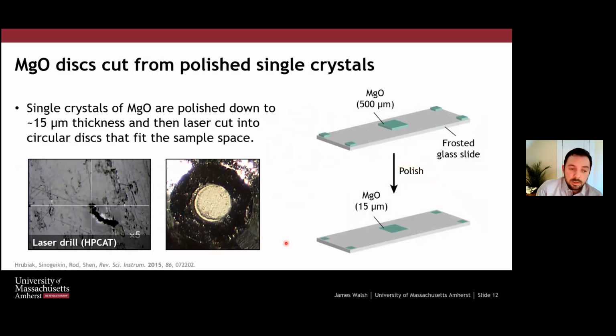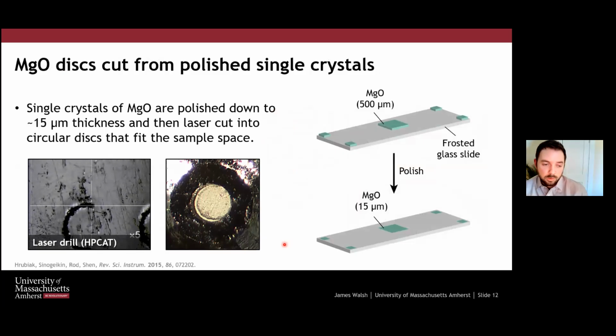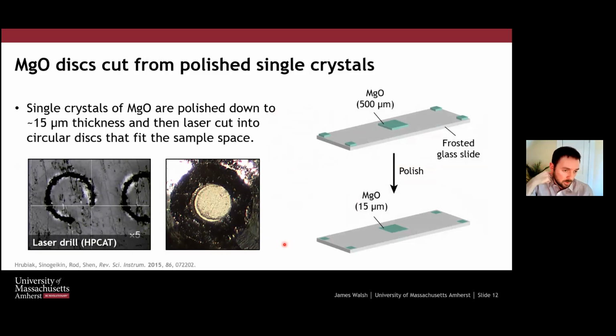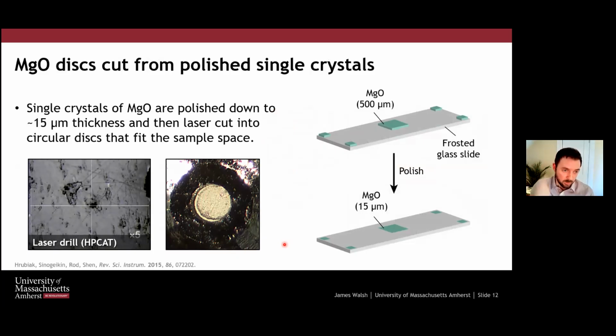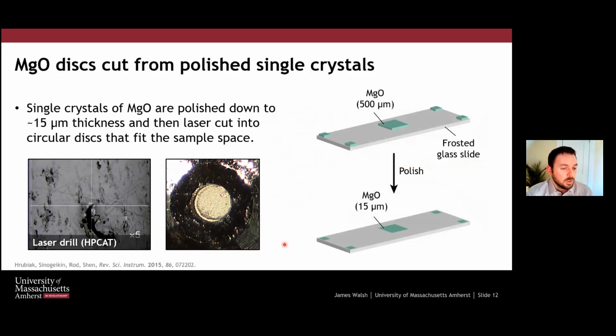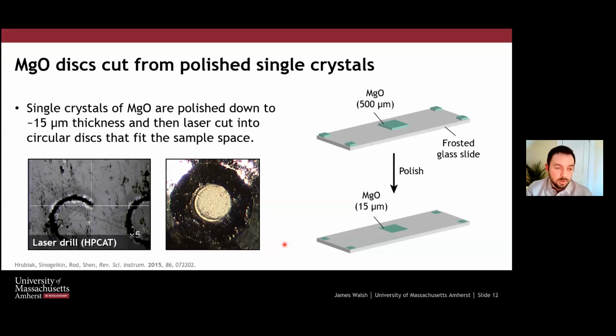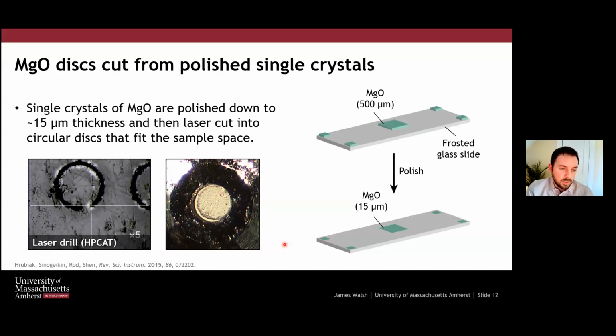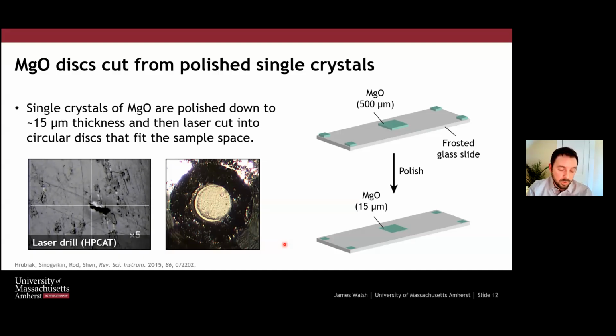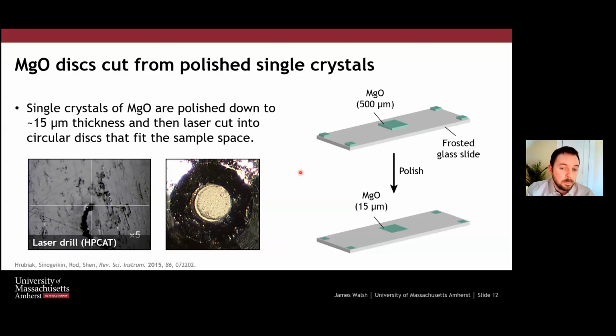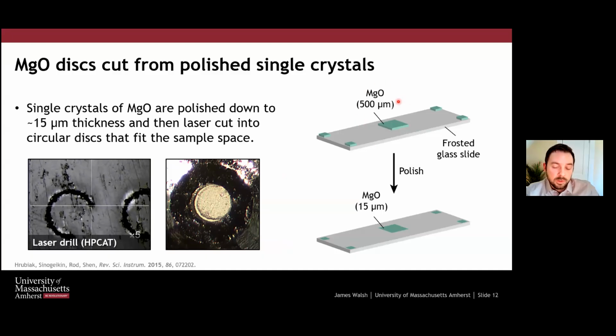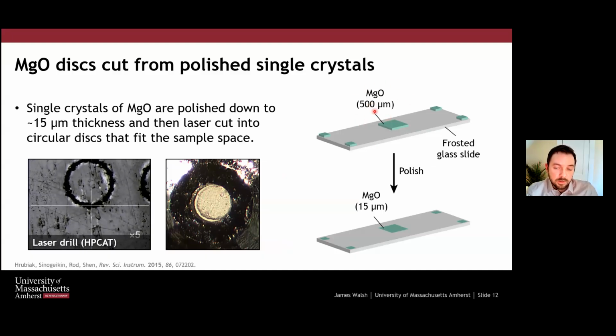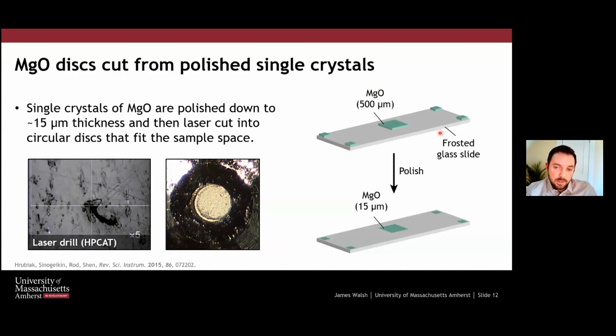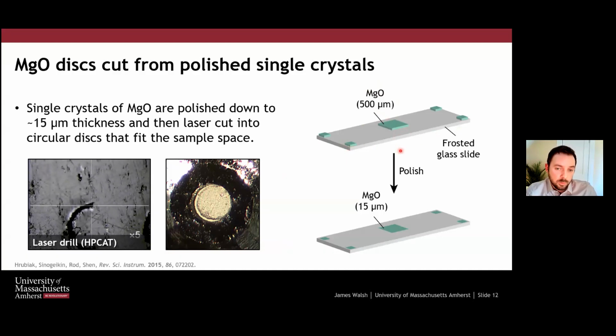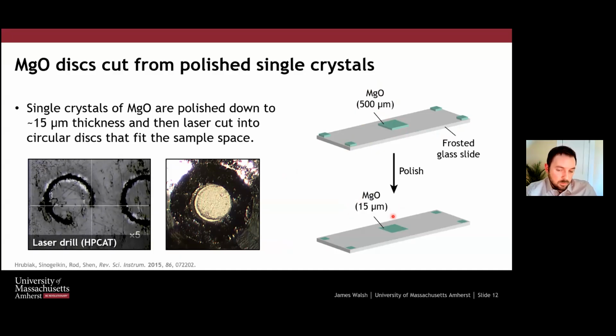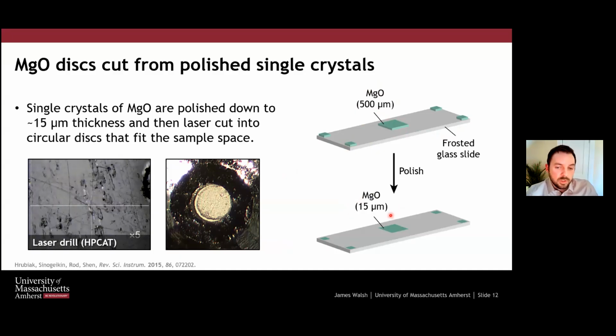Here's how we make the MgO. This is a technique that we learned from the staff at HPCAT, Ross and Yue in particular. I'm showing it here because I think it's something everyone should be aware of. I think a lot of you already do use this, but if not, you should really look into it, because for synthesis, it makes so many things much more straightforward and repeatable. We take a single crystal of magnesium oxide. Usually it's pretty thick to start with. We attach it to a glass slide with glue, and then we grind the sample down. We aim usually for our experiments to a final thickness of around 15 microns.